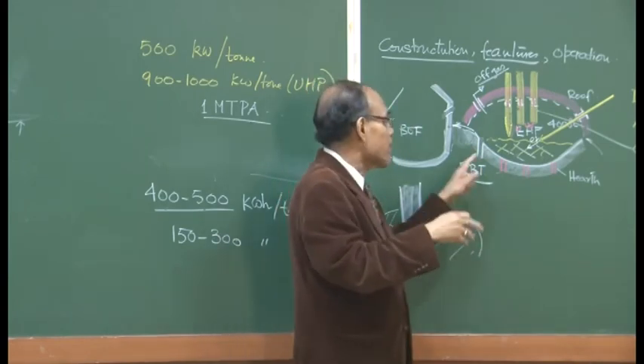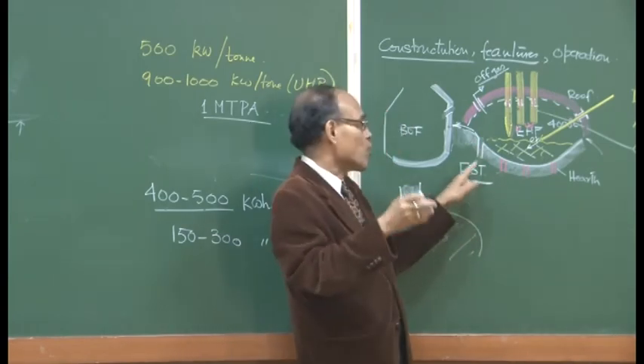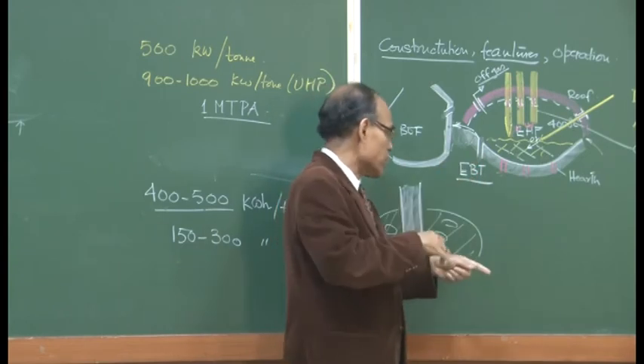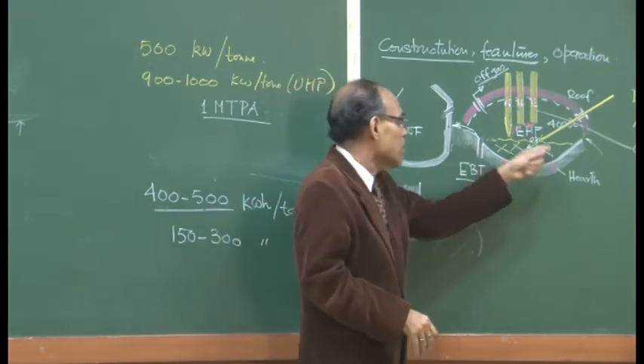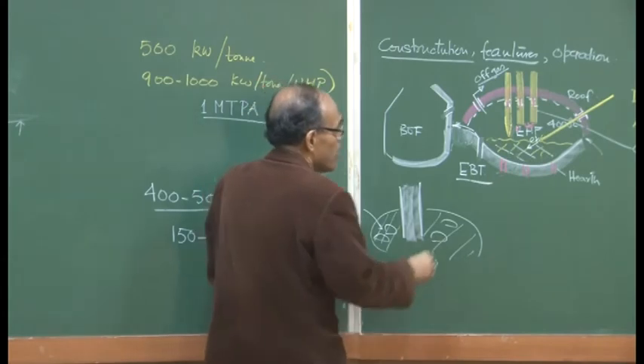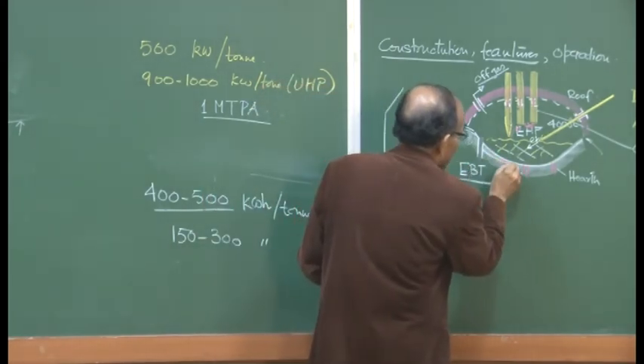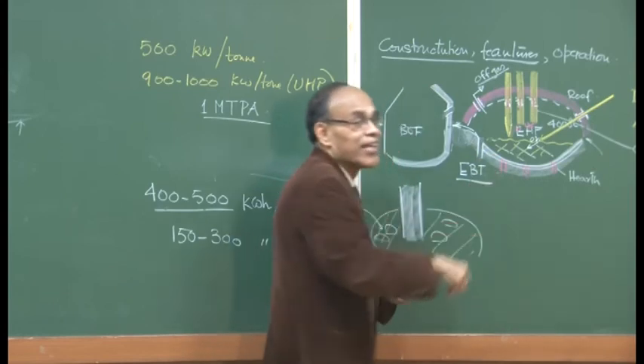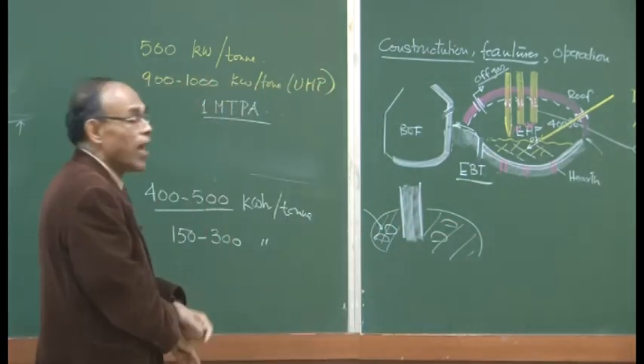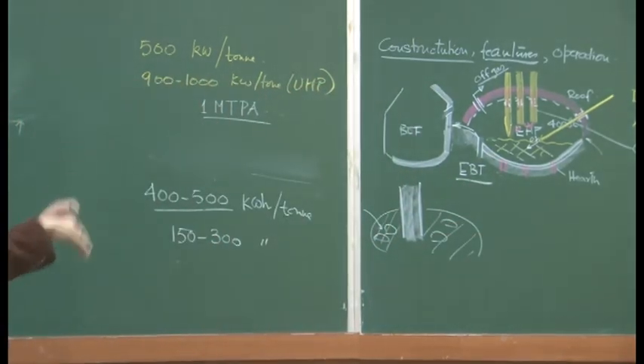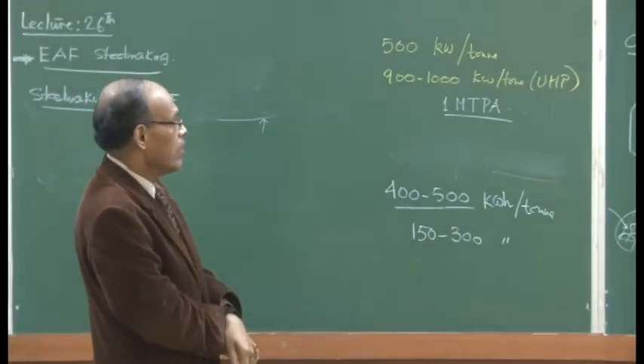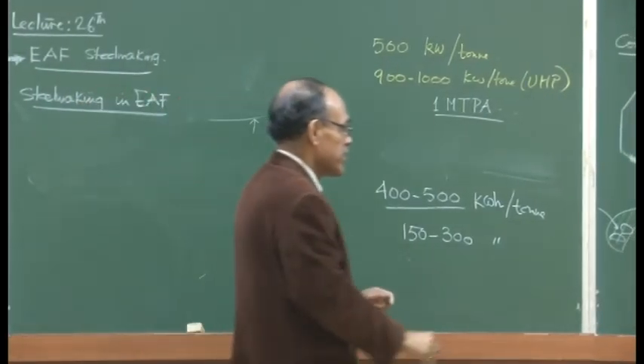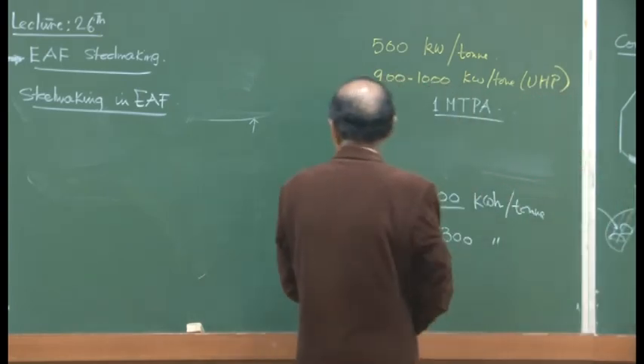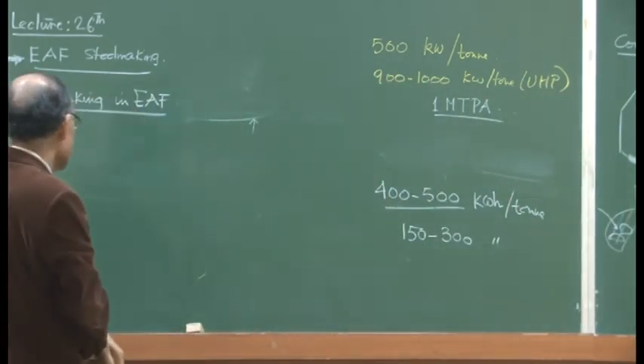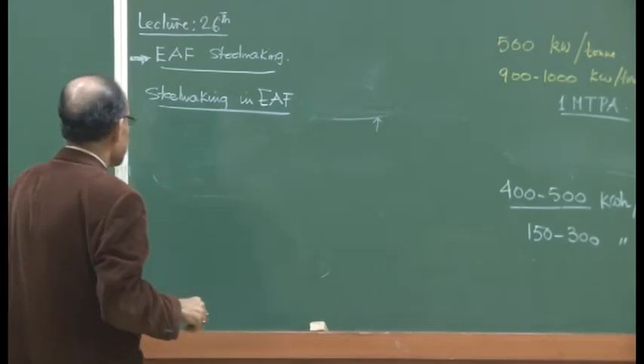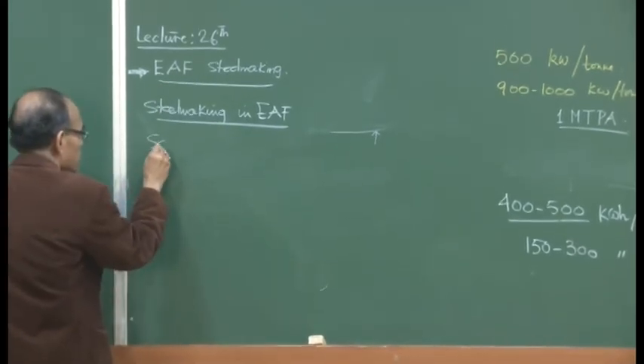After tapping you can tap metal, and then subsequently you tap the remaining slag, inspect the surface. Similarly, here also, as you can say, we have a working lining and we have a permanent lining of the base. The same kind of a construction goes on, and as I have indicated earlier, they are all basically basic material. Here it is magnesite based, and at the top it is chromite based magnesite for the roof because of different thermal requirements.